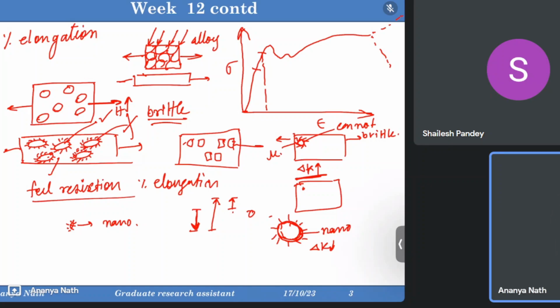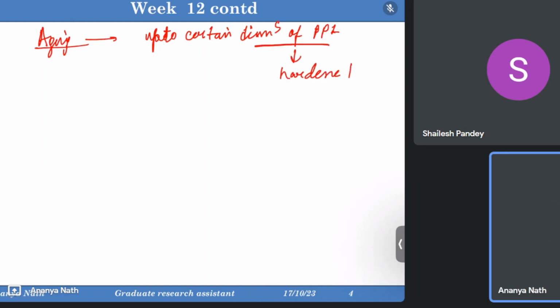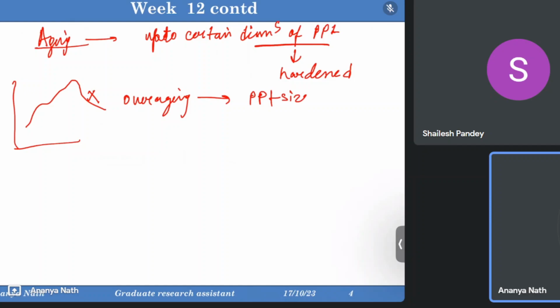So it's like for metal matrix composites. For alloys, I can take the example of alloys. What is aging? When you achieve up to a certain dimension of the precipitates, then we say that it is hardened. But do we go beyond this point? No. This is overaging. What happens in case of overaging? The precipitate size increases, due to which the hardness doesn't increase, rather the ductility increases, meaning the hardness decreases, because there will be a lot of space for the dislocation to move through the precipitates. So this happens in case of overaging.